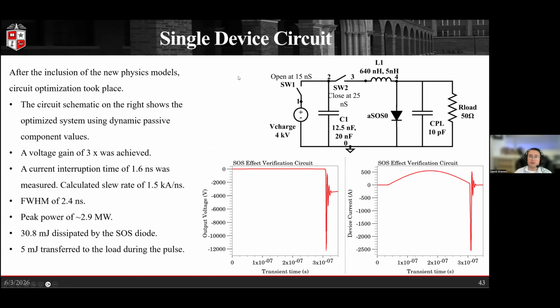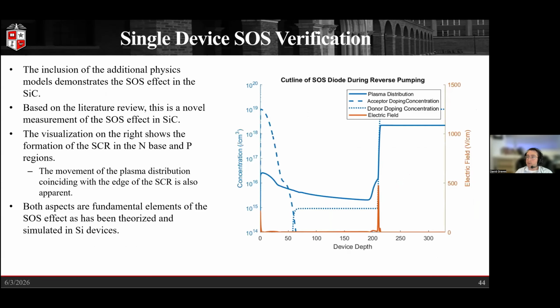So applying all of that together and optimizing the circuit around it, we can see that we can get a 3x gain for our device. So if we do a charge voltage of 4 kV, we're getting about 12 kV out. With this, we have a current interruption of about 1.6 nanoseconds, giving us a slew rate of about 1.5 kiloamps per nanosecond. Our full width half max of our pulse delivered to the load is 2.4 nanoseconds, and we end up with a peak power of 2.9 megawatts. And then we end up with 30.8 millijoules being dissipated by the SOS diode, with only 5 millijoules being transferred to the load. But we're able to optimize that.